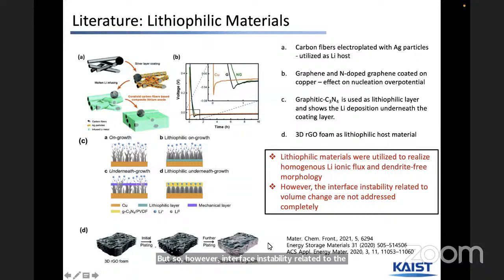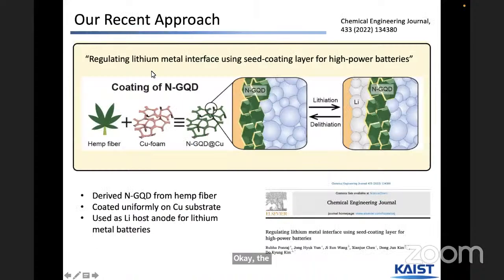Okay, the last example is our work. So now, for a few minutes, I'd like to present our recent work. We try to regulate the lithium metal interface by using a seed coating layer for high power lithium battery. We make a hemp fiber, this is industrial hemp, with a copper foam as a current collector, which gives nitrogen-doped graphene quantum dot coated copper. On the left side is copper, and I would like to put a seeding layer on there.